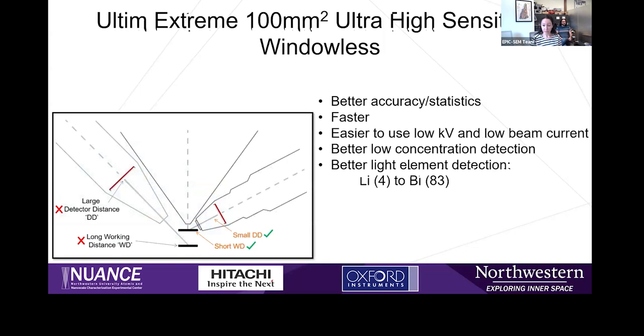If you remember from your general SEM training, being close to the objective lens or being at a short working distance is better for high resolution imaging to get a smaller spot size, and also so you can use an upper or through the lens detector system, which are higher resolution. Often with EDS, we sacrifice image quality by choosing parameters better for those EDS count rates, things like working at 15 kV or above, using higher beam currents, and longer working distances so that the X-rays will go into the detector. And all of these decrease your spatial resolution and can also sometimes increase sample damage and charging. So this is another great thing with the Extreme: you can pretty much just choose your parameters for that optimal high resolution imaging and analysis, and you don't have to change things for your EDS analysis.